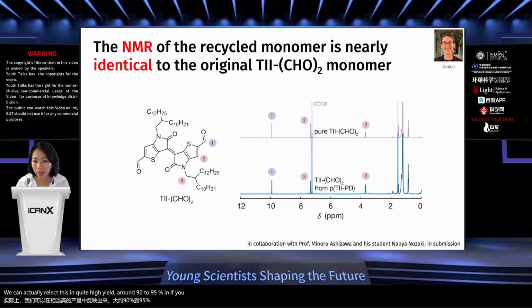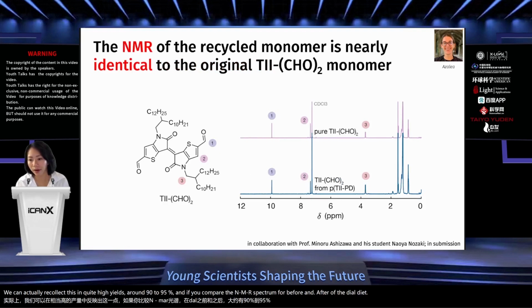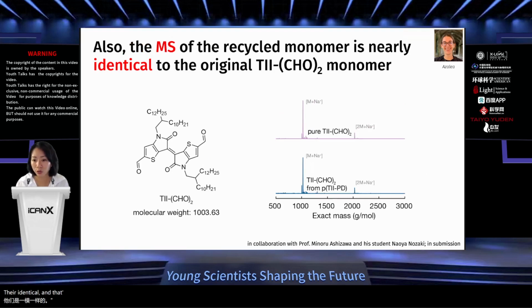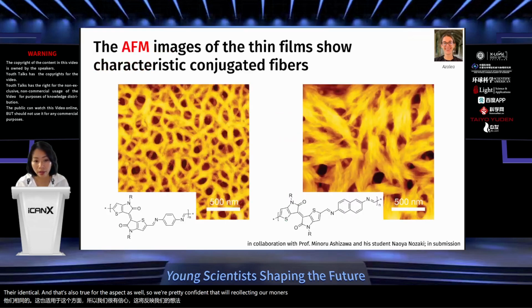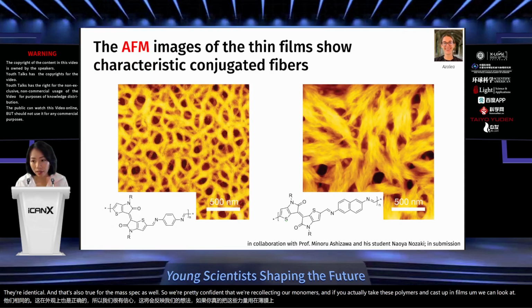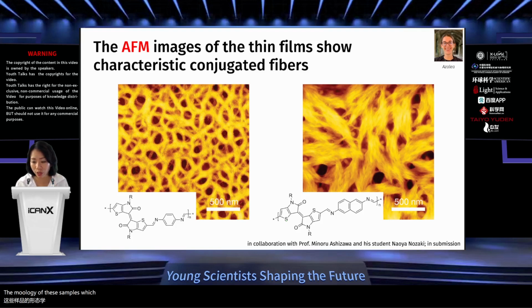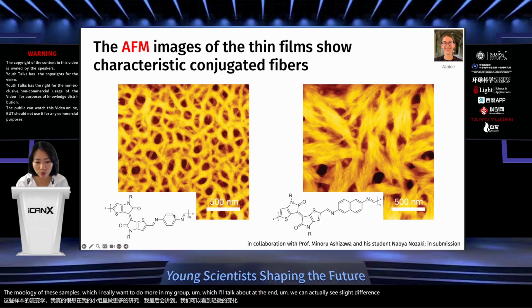And if you compare the NMR spectra for before and after of the dialdehyde, they're identical. And that's also true for the mass spec as well. So we're pretty confident that we're recollecting our monomers. And if you actually take these polymers and cast the thin films, we can look at the morphology of these samples, which I really want to do more in my group, which I'll talk about at the end. We can actually see slight differences as we vary what our diamine is here.